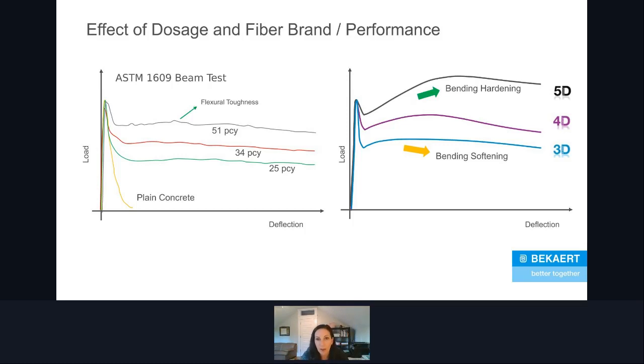So on the right-hand side, if we compare the same dosage, the same length, the same aspect ratio, but change the fiber performance class, in this case 3D, 4D, and 5D, if we remember, the difference is the anchorage and the tensile strength. And so you notice that the post-crack performance does differ pretty significantly. With many aspects being constant, but by changing those two factors, we really do see different performance.